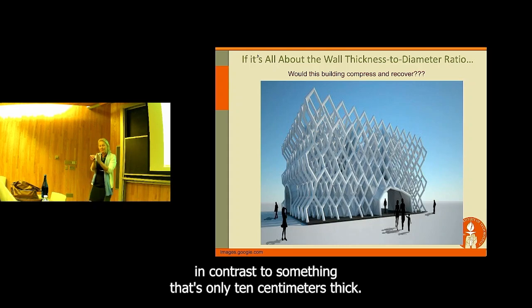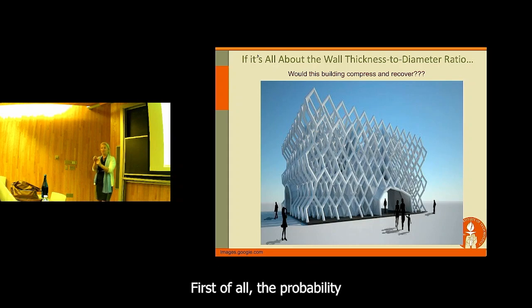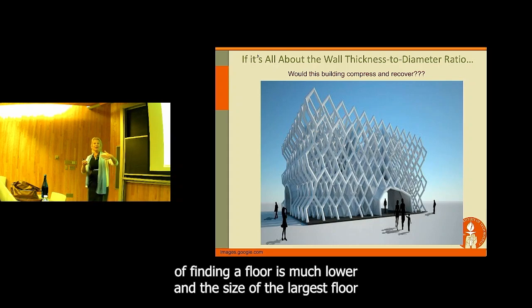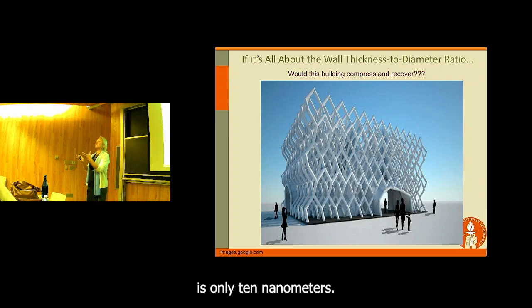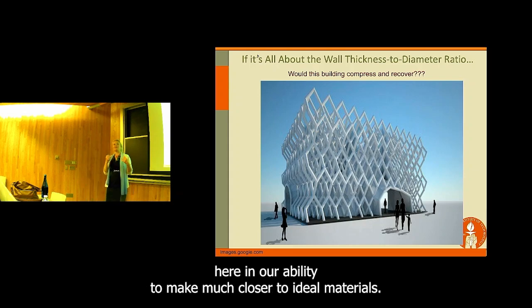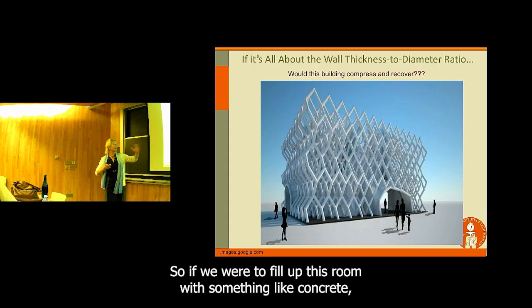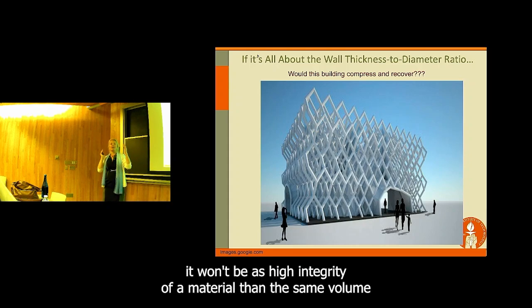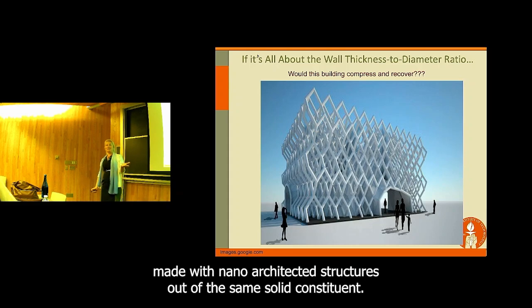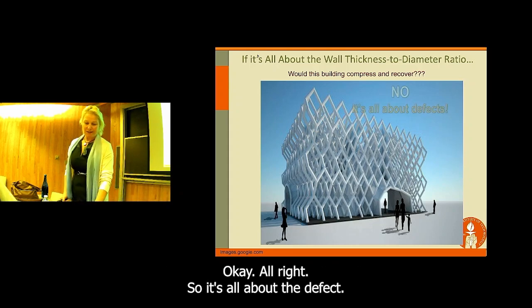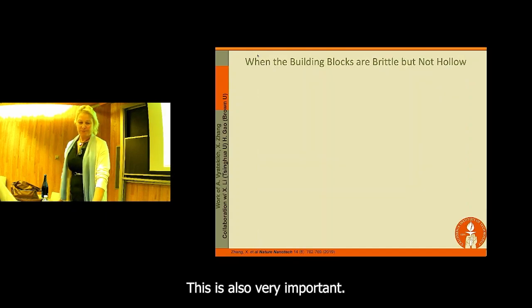In contrast, for something that's only 10 nanometers thick, the probability of finding a flaw is much lower, and the size of the largest flaw is only 10 nanometers. So the size effect manifests itself here in our ability to make much closer to ideal materials. If we were to fill up this room with something like concrete, it won't be as high integrity a material as the same volume made with nano-architected structures out of the same solid constituent. Okay, so it's all about the defects. This is also very important.